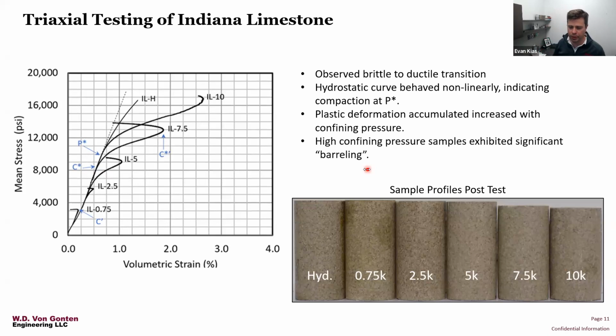I'm definitely not an expert on permeability and oil production, but what I've seen is that the compaction we observe, in other words the shear enhanced compaction in these samples, has a big impact on the pore pressure in the sample. In some cases we see a much greater increase in pore pressure during the triaxial stage, where you're applying a constant boundary condition, than in a hydrostatic state. So what that means is you're affecting your pore space differently. You can think of it like kneading a piece of dough versus just squeezing it all around. The changes in the geometry of this pore volume could have a big impact. Does it close? Does it reduce production, or does it enhance production? That's something I personally am not sure of yet.